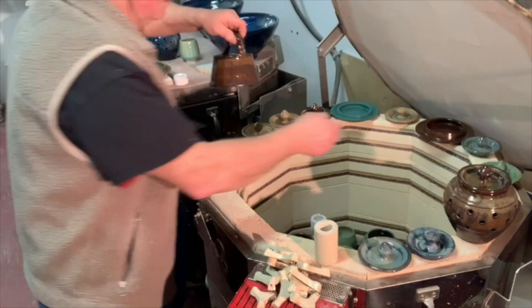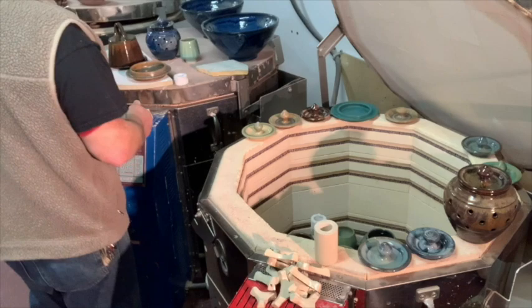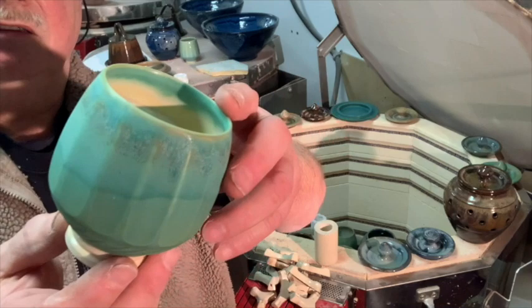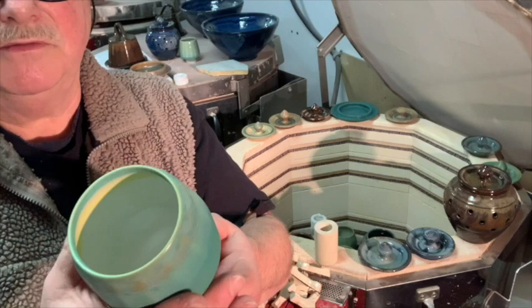And there you go, fits again. So a little butter dish or cheese dish, probably butter. Now, these cracked in the other kiln, so did they crack in here? Only one survived in the other kiln, because I love this color, but it's having dunting issues, and this is B mix 5. This firing was to cone 5. So I think if you take it to 6, the B mix with this glaze on it doesn't survive.